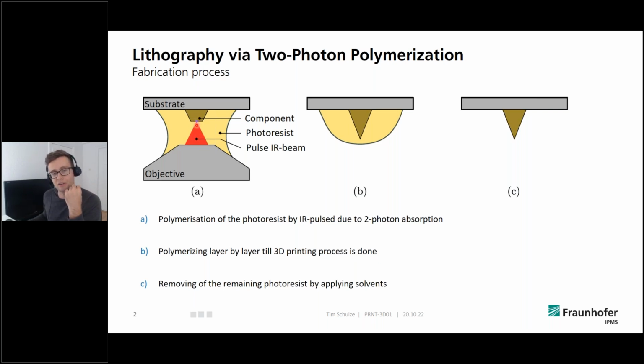But in the center of this beam, in the focus, the intensity is so high that it can happen that two photons are absorbed at the same time. The energy of two photons absorbed at the same time is equivalent to the absorption of one UV photon. That's why the resist polymerizes, but only within the small volume in the focus. This focus is also known as the voxel. The beam is scanned through the substrate, thereby creating different structures, and we can build a lot of interesting things.